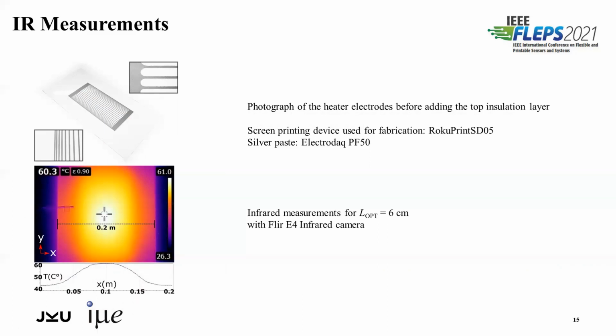We can conclude that the results are sufficient compared to the FEM simulations, and the uniform distribution is clearly visible within a certain error range. The reasons for deviation could be a variance in the print of the electrodes or other involved layers, and too small spatial dimensions of the sheet metal in Y direction. But we will address this challenge in future works.